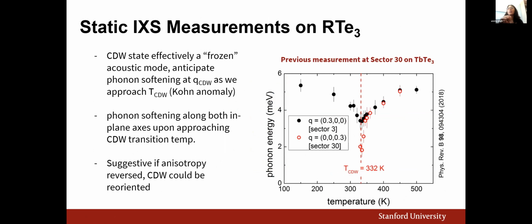And interestingly, what we see in those measurements, as we approach the CDW transition in these materials, is a softening of a phonon mode at the CDW wave vector. But we see that softening actually along both the C and A directions, although the phonon mode then softens completely along the C direction, where we see the CDW transition and long range CDW order take place.